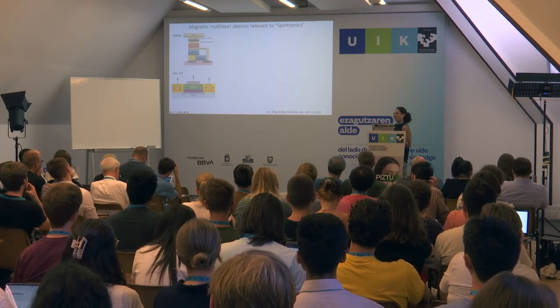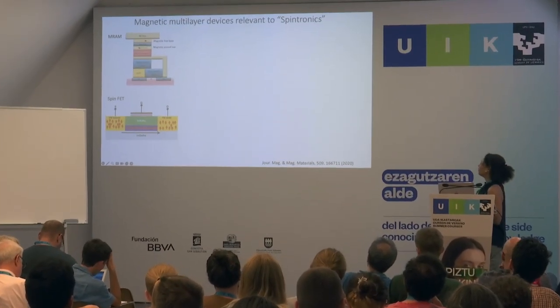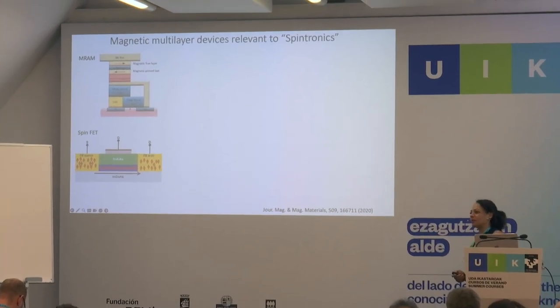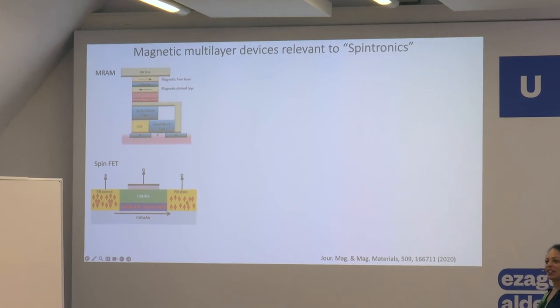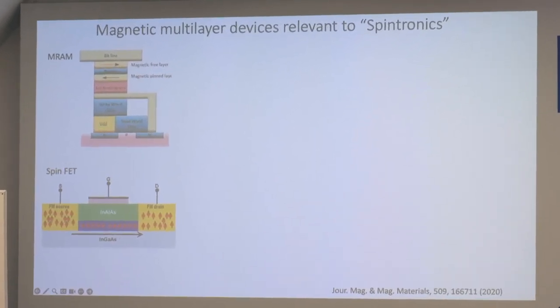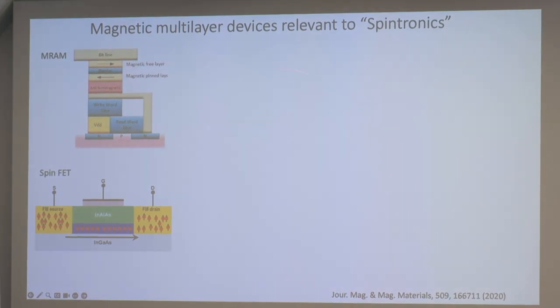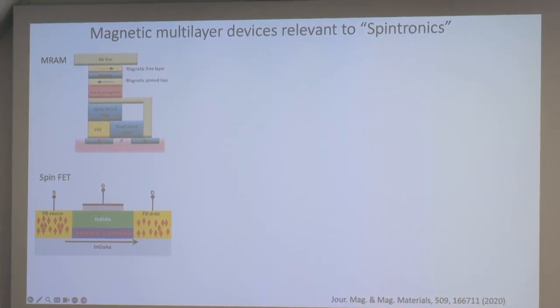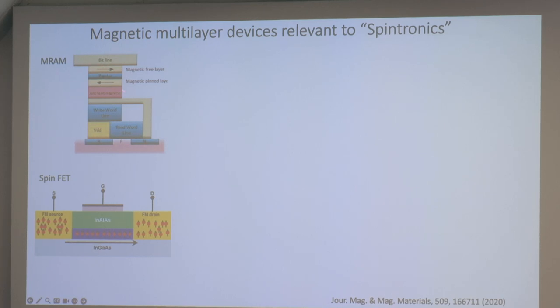So the other reason that these sort of heterostructures are interesting is because, again, we're talking about magnetic devices, and so I have three device slides again. But if you're wondering what the possibility of using topological materials in spintronic devices is, which I wonder about, then most spintronics devices are in fact magnetic multi-layer devices. So you take one of the most famous magnetic devices, that's MRAM memory, which is used everywhere. And that's a combination of having a magnetic free layer and then another material and then another magnetic layer. You can see that this is a layered magnetic material, right? So it's not intrinsic magnetic materials, but rather layered magnetic materials.